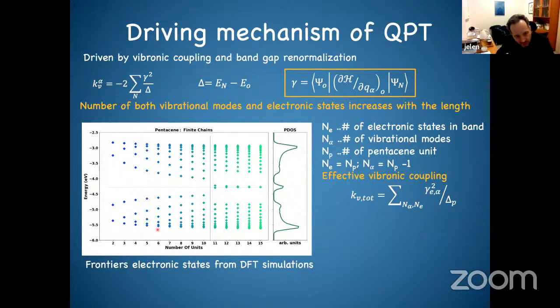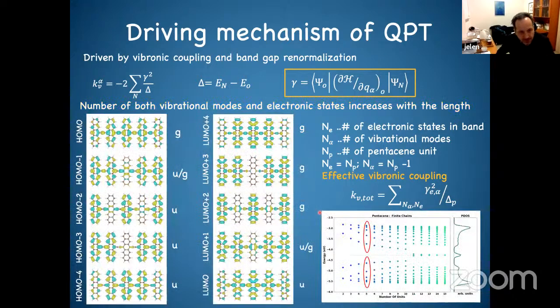And then when you go growing further and further, you have more and more states which develop in the band. Now, if I have a look at this, let's say 5, what you will find, and that's what I've already shown you before, is that when I have this band gap and I go into the conduction and valence band, I go to the mixed state. So the states at gerade and ungerade are different. Okay, they have different symmetry. So for example, this one here always has a bonding state here. But now I go to the LUMO, and actually now I start to see that here there are some bonding states.